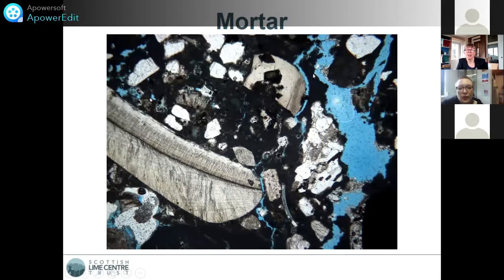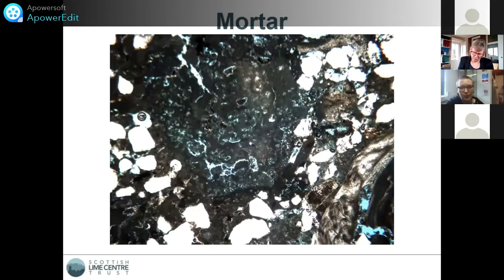And here on the right hand side, you can see there's quite a big space here, a big bit of porosity. And this is very common when you're looking at mortars, because especially in a harling, which is on the outside protecting the building, you get a lot of moisture movement travelling through. And when that happens, parts of the binder, which is calcium carbonate, will dissolve and be redistributed elsewhere. And that's an important thing to look at when you're trying to work out how that material is performing in the building. And this is an image of one of the lime inclusions here.